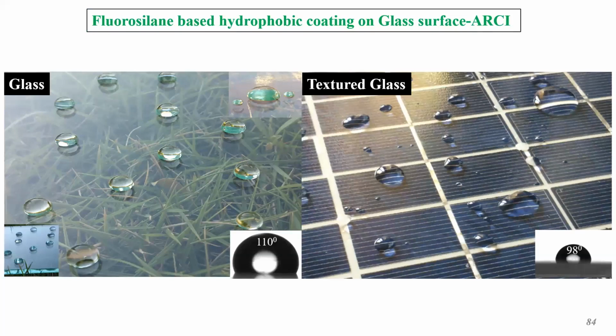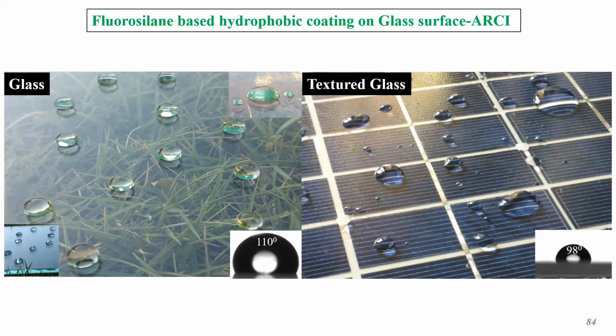And the same material, when I add fluorosilane, I got a hydrophobic property. I am not discussing this in detail, but this is a hydrophobic material with a water contact angle of 110. When we put this type of material on a solar cell, it cleans the surface very easily. So this was one of my researches in anti-reflection coating.